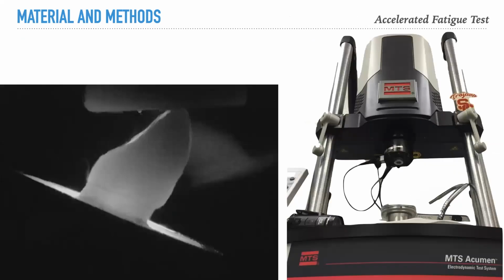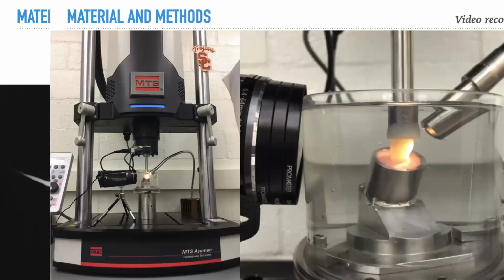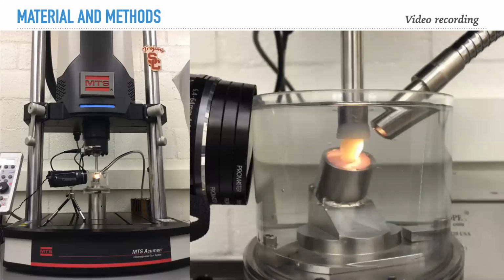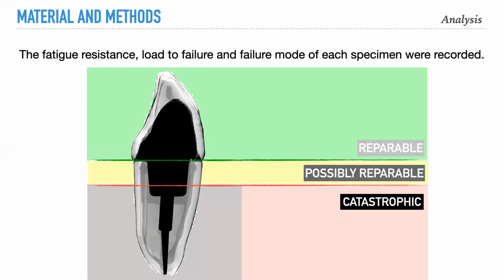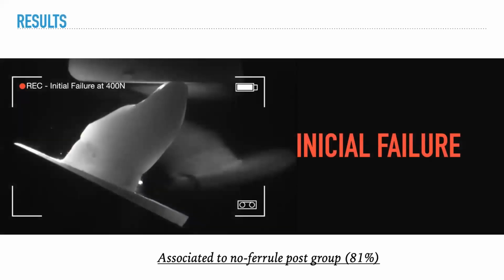So all the samples were submitted to fatigue forces simulated in an electrodynamic machine, and all the tests were monitored using a macro video camera and recorded continuously in order to determine the crack propagation mode, the initial gap, the root fracture, and the final fracture. As a result, we evaluated the fatigue resistance, load to failure, and failure mode of each specimen. And we can see here how the specimens were analyzed about the failure mode: repairable, possibly repairable, and catastrophic failures. The results of this study, we can see that the groups without ferrule present the initial failure.